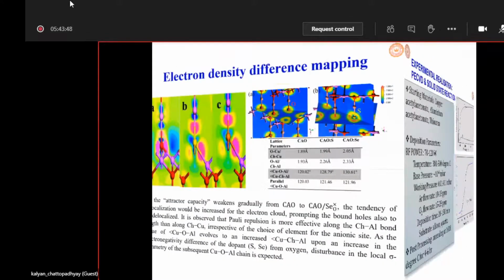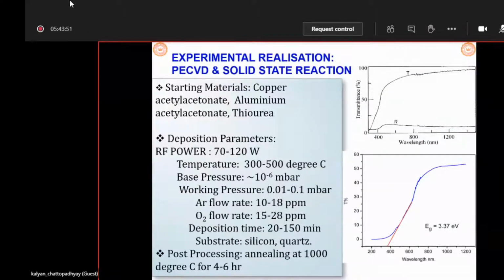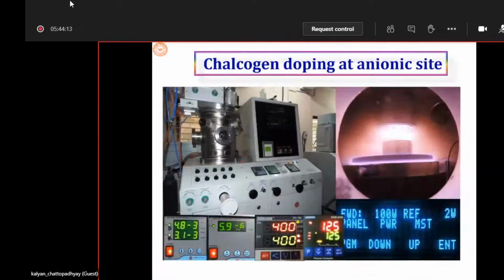Now, coming to the experiment, we performed both solid state reaction and thin film deposition by chemical vapor deposition, using organics, for example, copper acetylacetonate as the copper source, aluminum acetylacetonate, and thiourea dissolved in some organics. This is actually a homemade CVD system. Only the vacuum unit was purchased from Shanghai. Every other part, for example, the gas introduction system and the electrode configuration, is made in-house at our university.